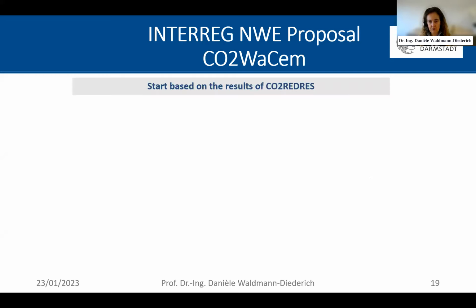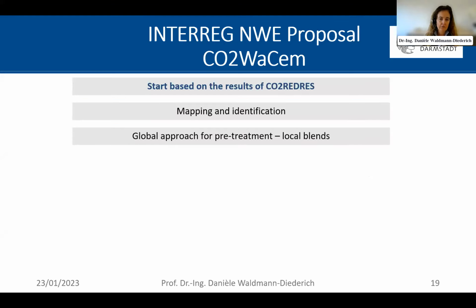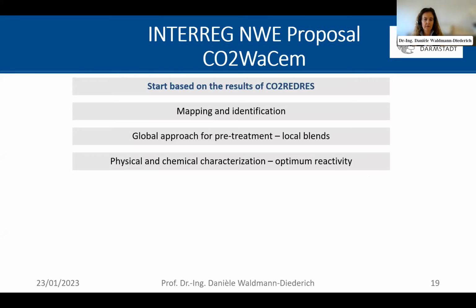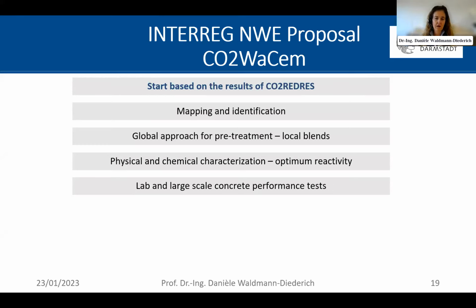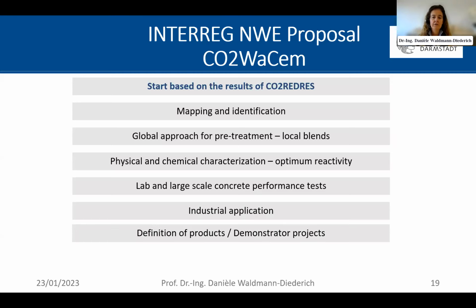In this new project, which starts with the results of CO2 Redress, we now try to map this larger area of Northwest Europe. We try to find more materials, and the difference from the CO2 Redress project is that, as we are aware that these materials are limited in quantities, we will now try to combine these materials locally into blends in order to have stability in properties over time, and to have larger volumes or quantities available, so as to come up with an economically interesting solution.